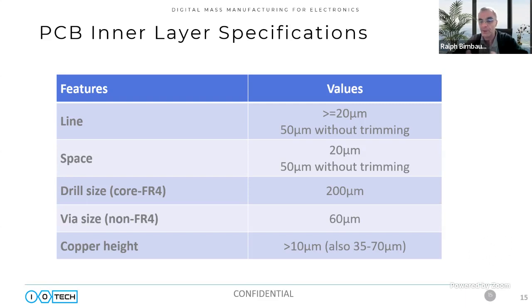We haven't yet built a multi-layer PCB with this technology, but if we were to do that, we would be basically printing the copper vias as we go up. So there will be no drilling involved. We can create such through holes of 200 micron, or via sizes as we build up of 60 micron, because that would be the minimum amount that we could fill the existing vias. And for copper height, we can print roughly 10 micron thickness, but of course, it's 10 micron and above. We could also go up to 35 and 70 micron. And if we print multiple layers, we can go above that as well.